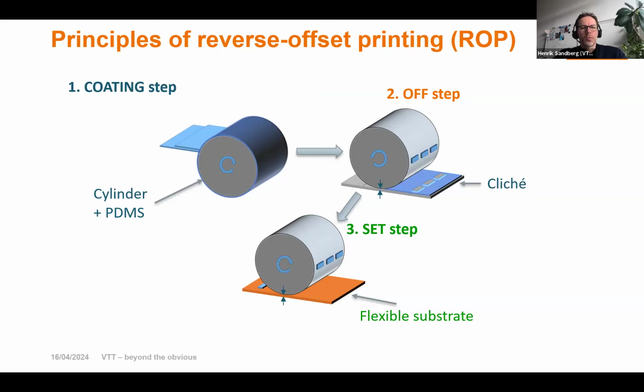Then the fully coated PDMS cylinder goes over a cliché, which is a patterned layer. In our case, it has a relief pattern. It can be a metal film, it can be a silicon wafer or glass wafer of some kind, but it has this height difference in the surface, and with this you remove all the material which touches the surface of the cliché, and then that's the off step. So you remove some material, and then after that comes the set step, when you apply the material which is on the roll onto your substrate, which is then usually a flexible substrate.